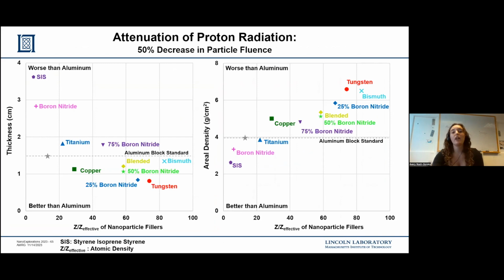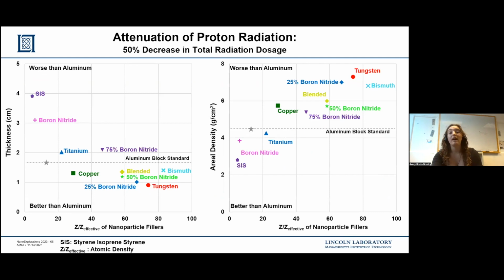So when we look at our 50% decrease in particle fluence, when we use thickness as our metric, our higher Z materials obviously outperform the aluminum block standard. Again, like heavy ion testing, when we change to areal density, our lower Z materials are able to outperform the aluminum block standard. The same is true when we look at the 50% decrease in total radiation dosage. The trend exists even though we have a slight shift in the thicknesses required, or the areal densities required.